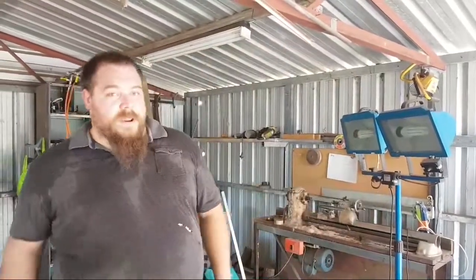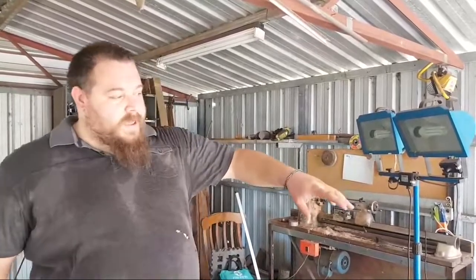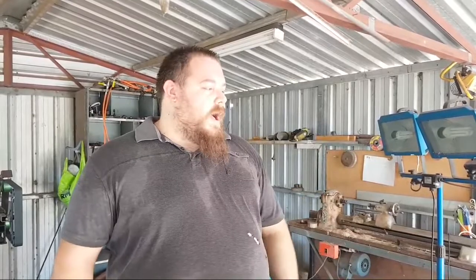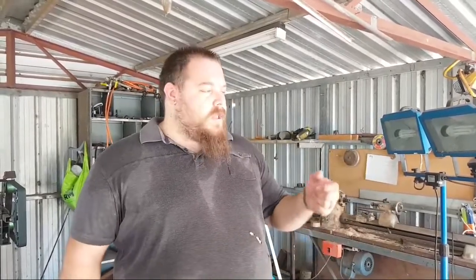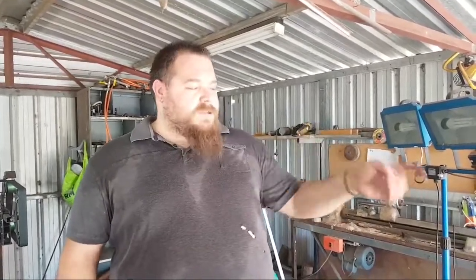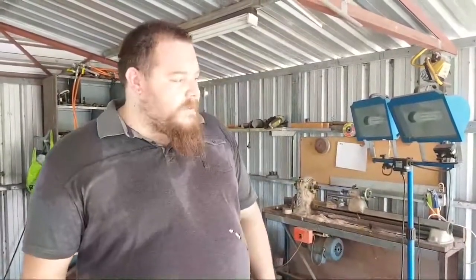But the main advantage of running a forge like this at this temperature is that basically I can just leave that hammer in there forever, and it's going to get up to the heat treating temperature and just stay there forever. I don't have to worry about overheating my billet or underheating my billet. I have practiced with this forge enough that I know what settings will provide what heat. If you have a new forge that you're trying to work on, you can just get a pyrometer and kind of play around with your settings until you get your perfect heat. I would suggest that for doing this kind of stuff, because obviously with a pyrometer you can reliably get heats. But I have practiced enough, and I know that I've got a kind of an area of effect that I can use for 1045. It's fairly forgiving steel.